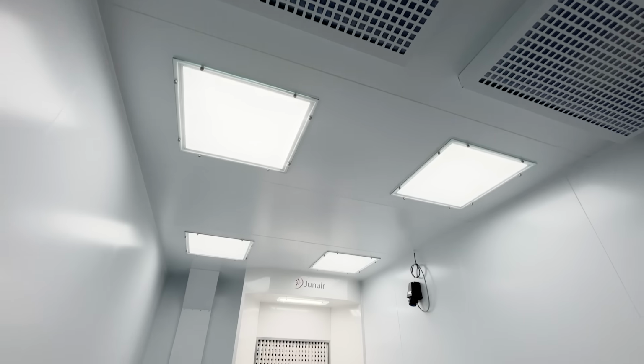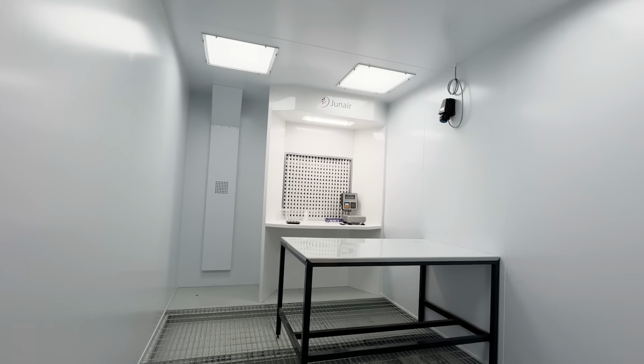Another important factor in your working environment is ventilation. In common with all polyester and vinylester resin systems, Uni-Mould releases styrene during cure and should only be used in a well-ventilated area or even outside. Generally, for smaller moulds, the passive ventilation that you're going to get by opening a window and a door will be sufficient to stay within safe limits. But for large moulds or in confined spaces, mechanical ventilation would often be needed. Note that styrene does have a very strong smell, even in concentrations well within safe limits, and so you might need to consider co-workers or even neighbouring buildings when you're producing moulds.